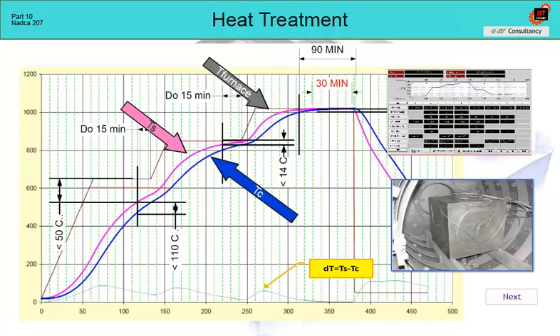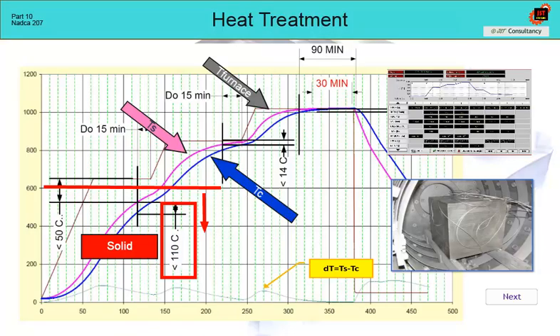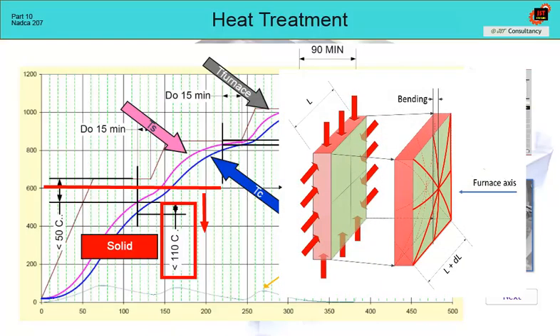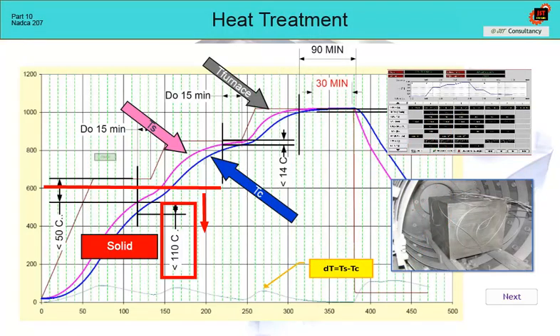When heating, it is necessary to take into account that up to approximately 500 to 600 Celsius, the material is in a solid state and is subject to stress from the temperature difference between the surface and the core. It means between Ts and Tc. Therefore, even before reaching this temperature, it is necessary to check that the temperature difference is less than 110 Celsius. Otherwise, there is a risk that either permanent deformations will occur on the part, or it may even crack. Only above this temperature does the material become plastic, and stresses are reduced and dissipated.